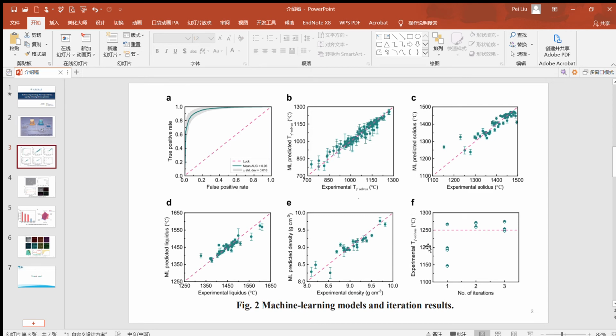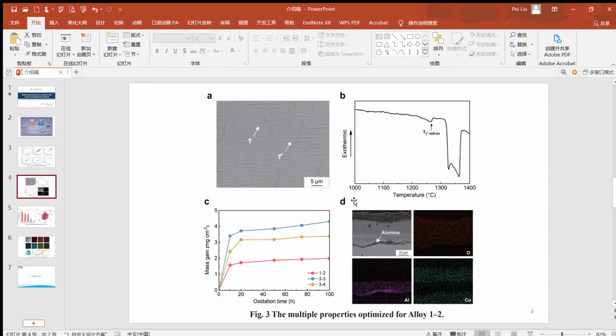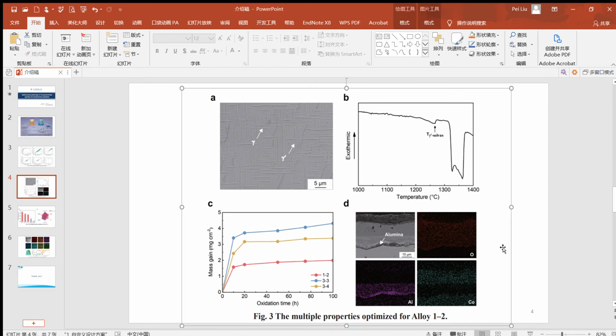With the experimental gamma-prime solvus temperature, we think after 3 rounds of iteration, the gamma-prime solvus does not increase significantly. Therefore, we stop this iteration. In figure 3, the multiple properties optimized for Alloy 1-2 are shown. You can see the microstructure is very good without the precipitation of any deleterious phase, and the gamma-prime solvus is very high, and the oxidation resistance is good due to the formation of an alumina layer.